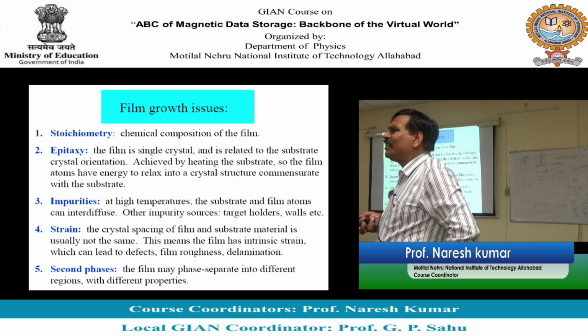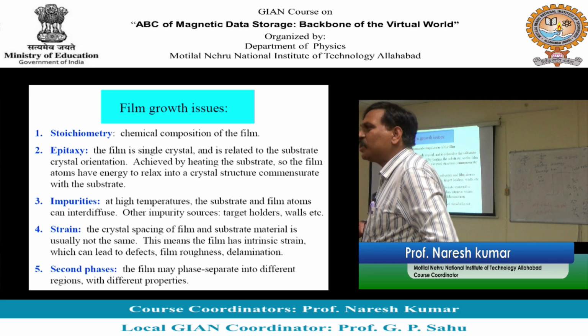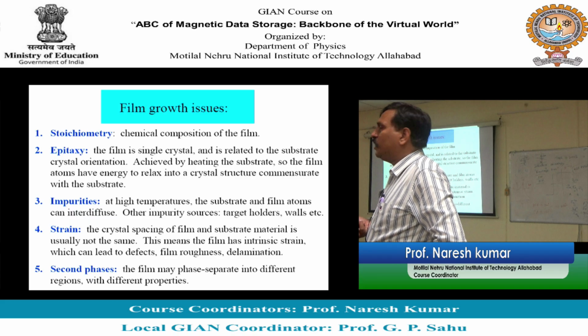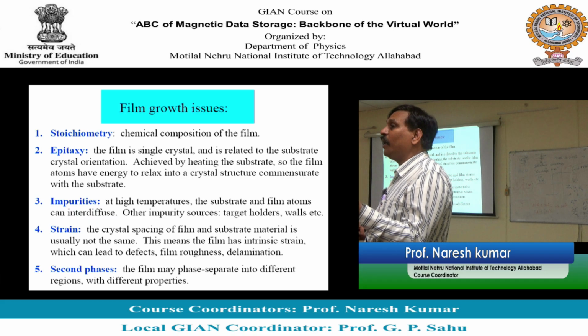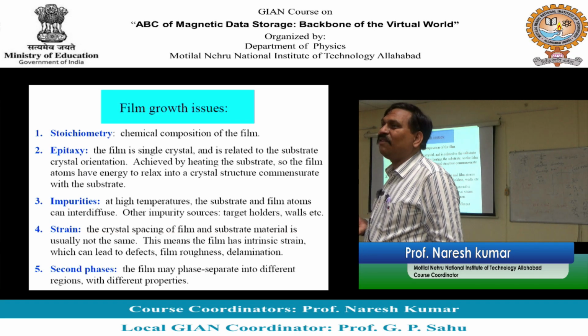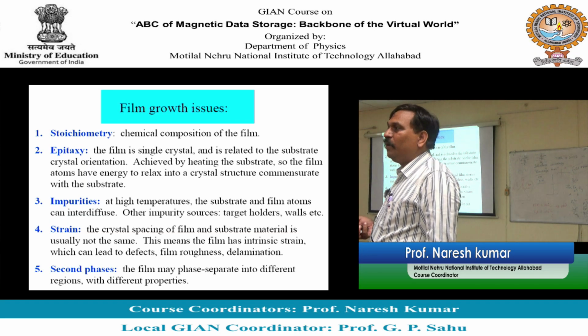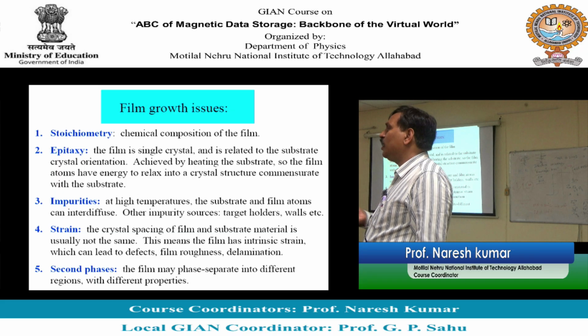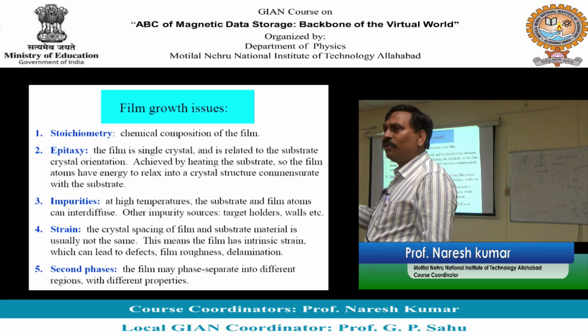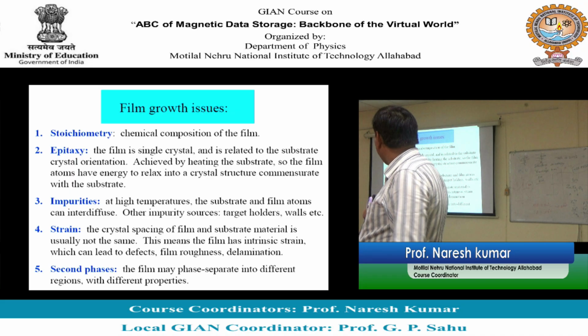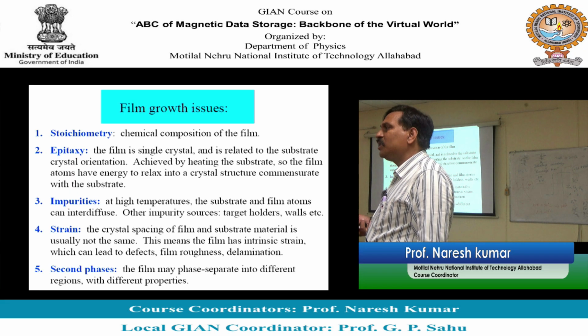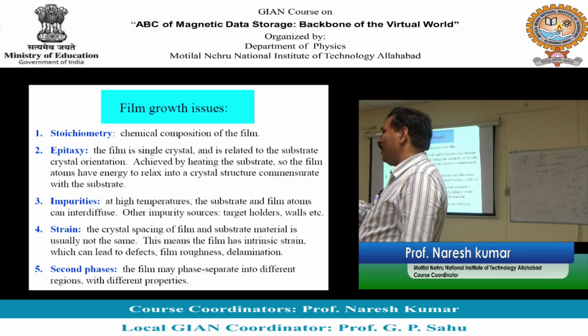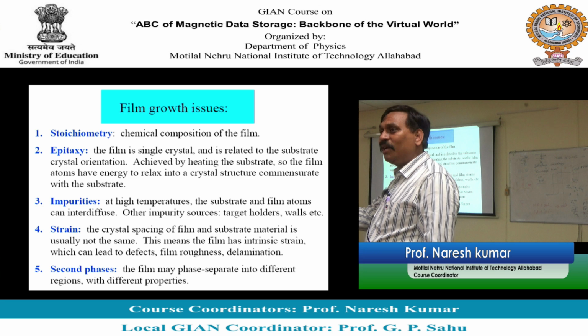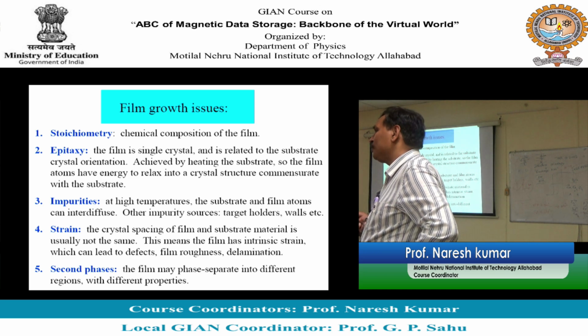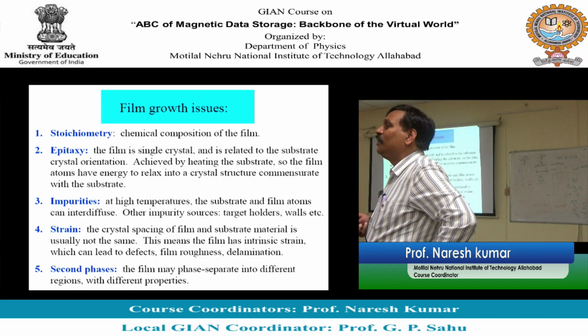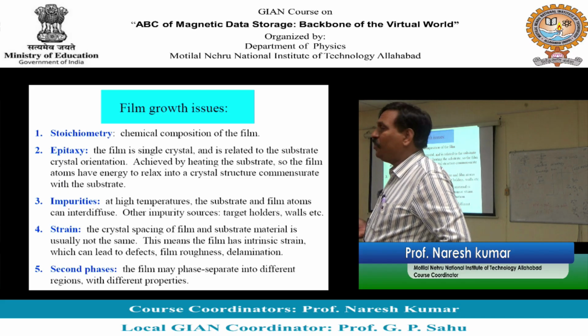As I said, sputtering is a commercially used thin film deposition technique. But if you are using a multi-component target, then with sputtering it is difficult to maintain chemical stoichiometry. Those who are working, let's say, with superconducting material, HTC, YBCO, there are 4 components. And if you try to make thin films using sputtering, because there are 1, 2, 3, 4, it is very important to maintain that. If you don't maintain that chemical composition, it will not be superconducting. So if you want to precisely control stoichiometry, then I think sputtering will be an issue.